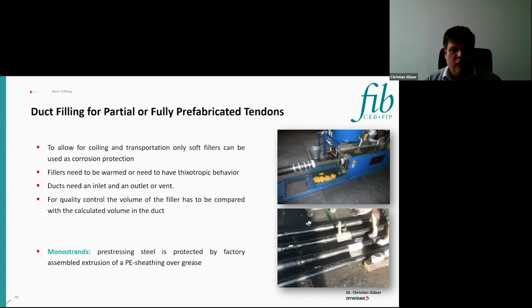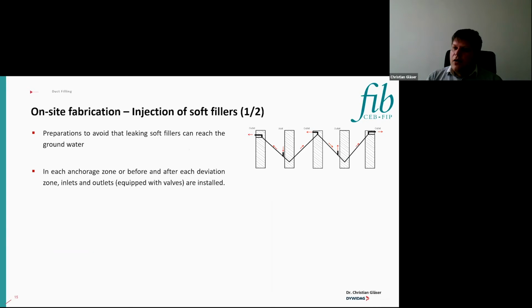In case of monostrand tendons, usually all the protection on the free lengths is directly done at the strand manufacturer. So usually the strand manufacturer is directly applying the extrusion of a PE sheathing over the grease layer on top of the strands. For on-site assembly, I'm focusing here on soft fillers, but in the Bulletin we are also describing it for cementitious grout.